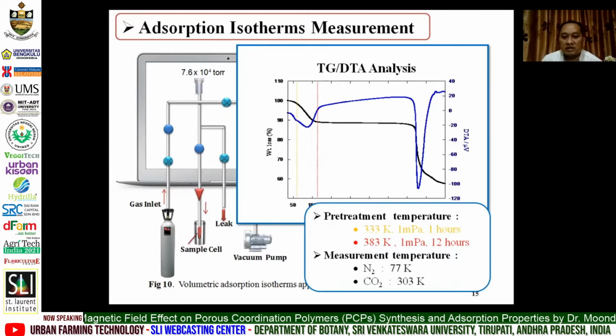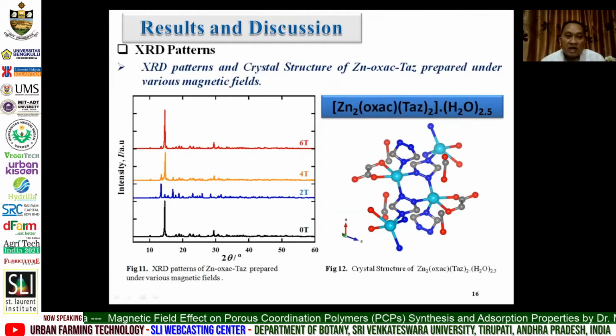Initial stage at 333 Kelvin for 1 hour, and then continue at 383 Kelvin for 12 hours. And then after pre-treatment temperature, the adsorption measurement for nitrogen and carbon dioxide: nitrogen adsorption at 77 Kelvin, and then carbon dioxide at 303 Kelvin. So this is the XRD pattern and the crystal structure of zinc oxalate TAZ prepared under various magnetic fields.